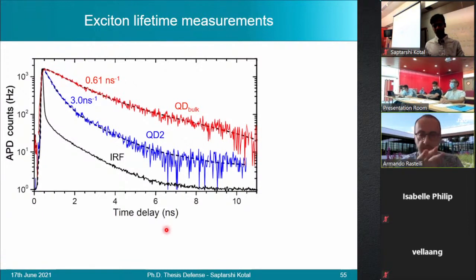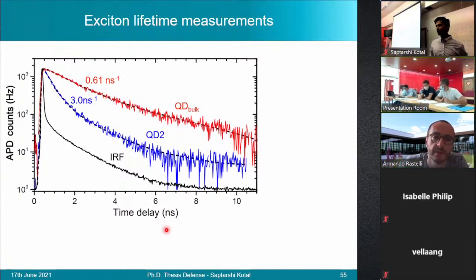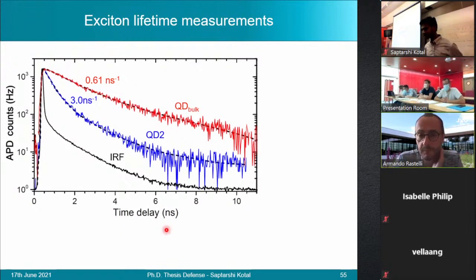I see. Maybe it's not strictly related to your thesis, but do you know if this spin flip is temperature dependent? So what do you expect? Actually, what is causing this spin flip? I mean, in principle, you need some sort of coupling between dark and bright states, right? Yes. So I think it has a temperature component to it. It must be coupling to phonons. There has been work done by my previous PhD student in the team on precisely these effects of spin flip in quantum dots. And there we noticed that temperature has a role to play in such spin flips.